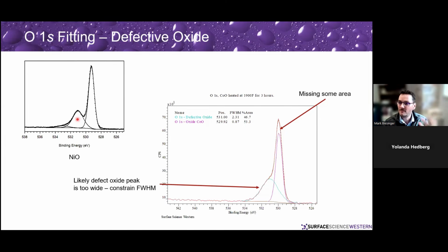But it can vary, and it really depends on how that material is treated. When you're doing curve fitting of these things, you want to watch your full width half maximums. You can see how in this cobalt oxide system, we've got this main peak and then this defective oxide or other thing. And this has been heated to 1900 degrees Fahrenheit, so it's very unlikely that there's much adventitious carbon left on that surface, depending on how clean the surface is, or that there's a lot of hydroxides present, that's for sure.